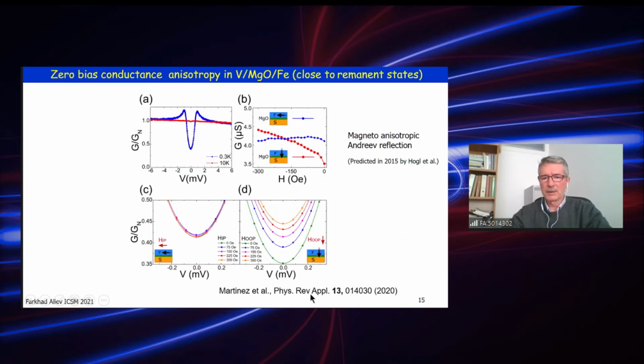As I mentioned, the first indication of possible long-range penetration was done in this paper, where we investigated at zero applied magnetic field, depending on orientation of the iron with respect to in-plane and out-of-plane, and we observed about 15% tunneling magnetic resistance at zero bias. We assigned this to magneto-anisotropic Andreev reflection predicted by theorists, and this was the first indication of possible long-range penetration of Cooper pairs in iron.